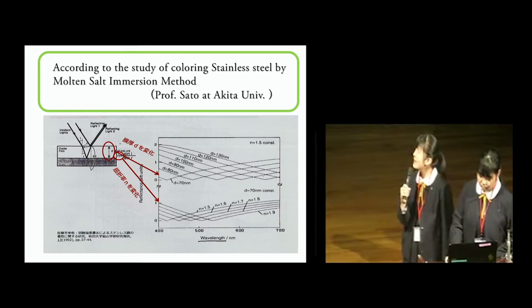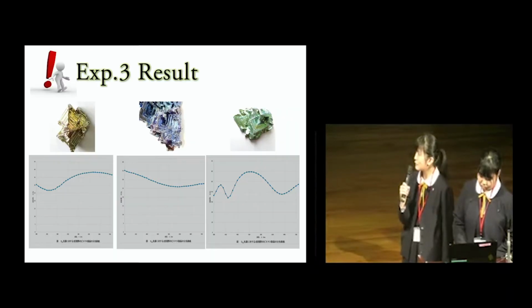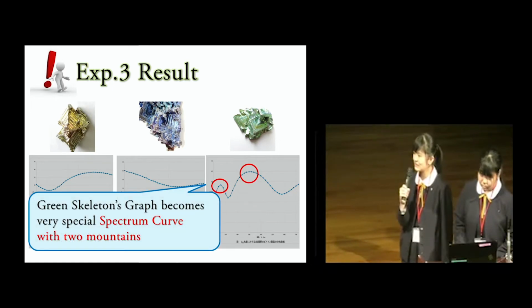Look again at the absorption spectrum of the crystals we created. The crystals oxidized to green by the anodic oxidation method have an absorption spectrum graph with 2 peaks. This result was interesting because it was impossible from Professor Sato's simulation. For this reason, we assume that the green crystal surface forms multiple oxide films with different degrees of oxidation. Therefore, an attempt was made to visually grasp the oxide film on the surface.